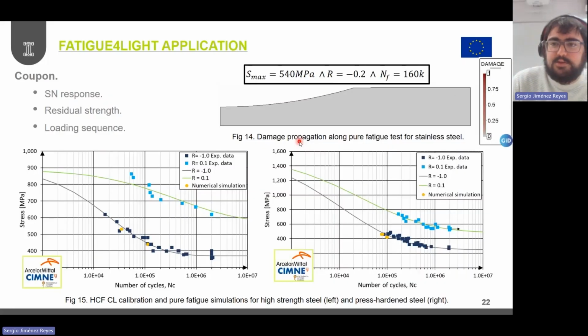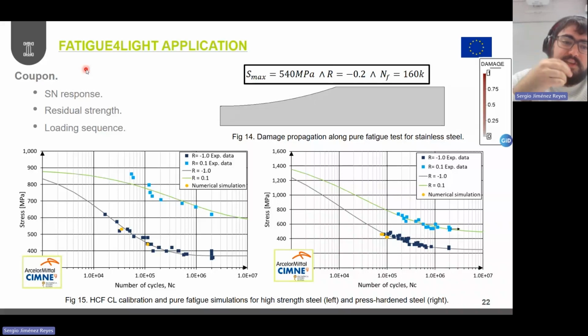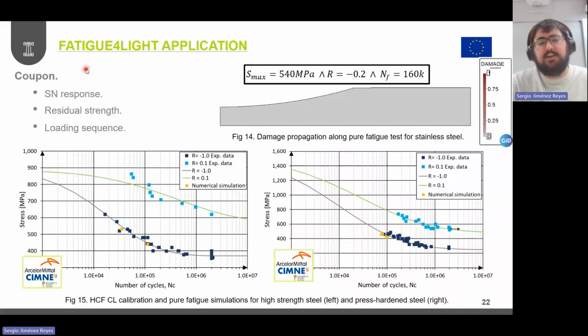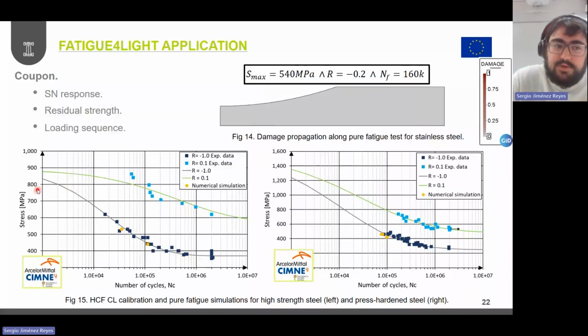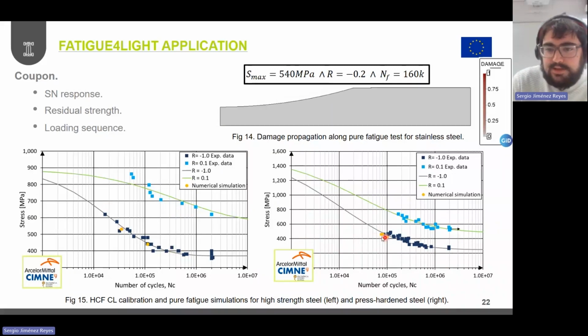And now let me just move towards some application examples corresponding to the Fatigue4Light project. So first of all, as Lucia mentioned, we dedicated the first year to study the material response of different materials that then are being used in the project to build the final Fatigue4Light solution for several demonstrators. So in this first stage, we calibrated our constitutive model, and we were able to undergo some of these pure fatigue experiments, reproducing some of the SN tests, and you have here some of the results obtained for high strength steel, and this one corresponding to a press hardened steel.